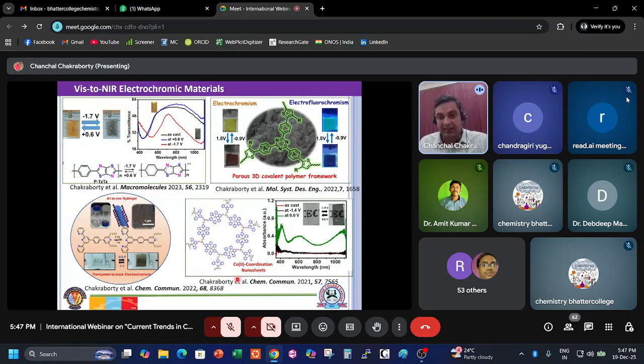But the thing is that we did not get that much color fastness, and also the color and efficiency are not optimum, and we are yet to get a truly visible to NIR absorbing electrochromic material which can block the sunlight at the highest level. So for that purpose, we developed a covalent organic framework basically, a covalent polymeric framework through perylene carboxylic anhydride along with melamine, and that melamine-perylene can provide this COF.